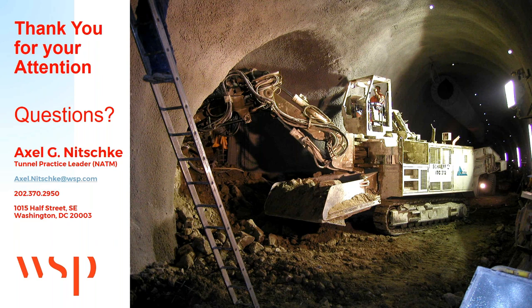The next question is: NIOSH has performed research on Shotcrete adhesion and found some materials — like weak shale — to be poor substrates for adhesion no matter how well the surface was prepared. What are your experiences with this? In tunneling, you have to deal with what Mother Nature provides. If you don't get adhesion to the substrate, you don't get it — but that doesn't mean Shotcrete stops working. You cannot use it structurally connected to that substrate, but it can still function. If in doubt, conservatively assume you don't have that structural connection.